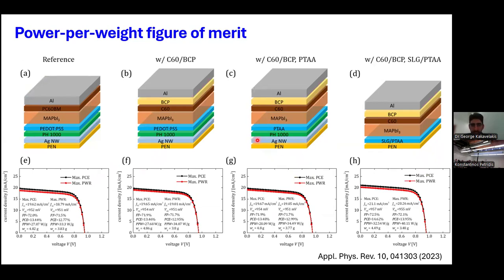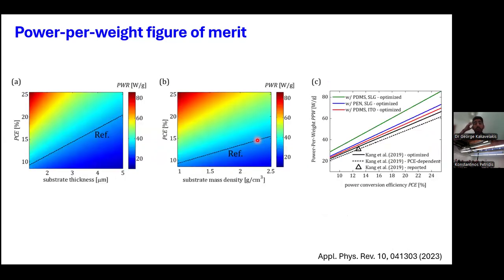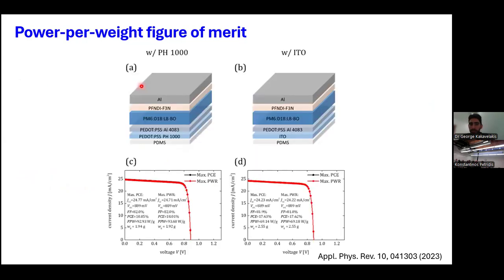Okay, and I will skip this part and go here to show you that we have also done a theoretical calculation, and we have seen that if we manage to use an extremely thin substrate, like this one of 1.7, keep this in mind, and we manage to keep a very high efficiency of 25%, this will give rise to a theoretical level of approximately 80 watt per gram. And you remember the value for crystalline silicon or other devices is less than 0.1. So it is a real breakthrough, a game changer regarding the power per weight figure of merit.